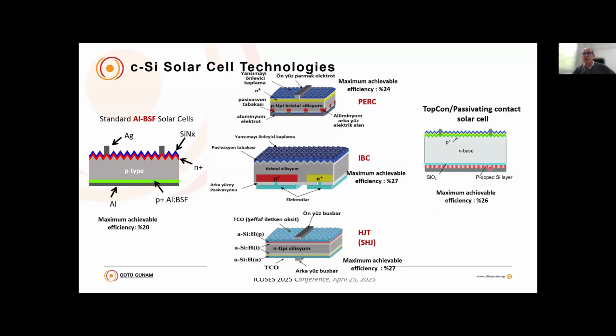Instead, we have a very tiny silicon dioxide layer, which is the blue one here, and on top of that we have a polysilicon layer. This polysilicon layer provides the necessary electric field on the backside junction to separate the charge carriers and reduce the recombination. When we remove the contact between metal and the silicon here, we obtain an excellent passivation on the backside. Then the efficiency has reached about 26%. At the industrial level, the efficiency is around 25.3% or so. The Chinese companies are now producing with such an efficiency value.